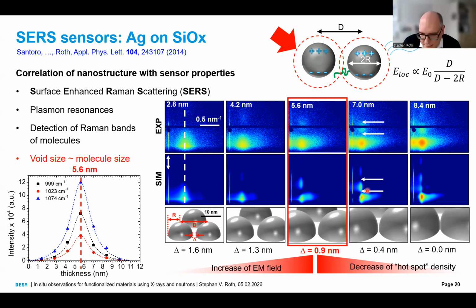So if you look also here, when you have clusters, you see this line here. It's a line. When they start touching each other and you approach the percolation, this becomes like a triangle. You see it here also in the simulations. And this is an indication of a percolated layer.